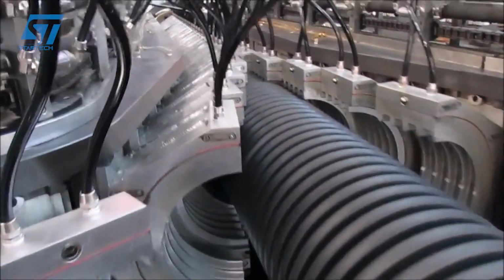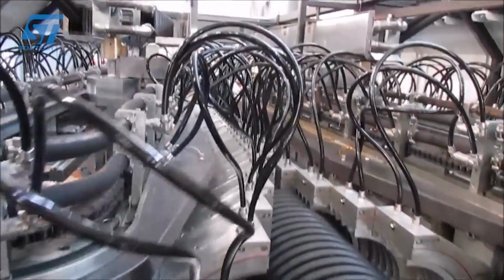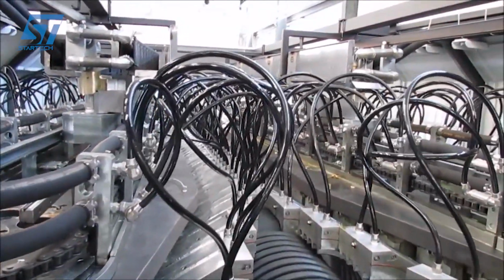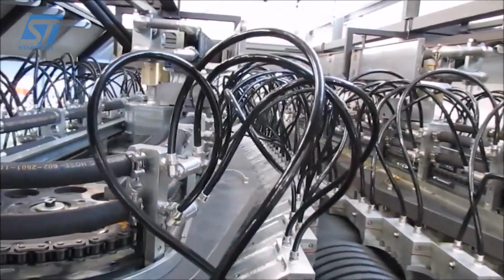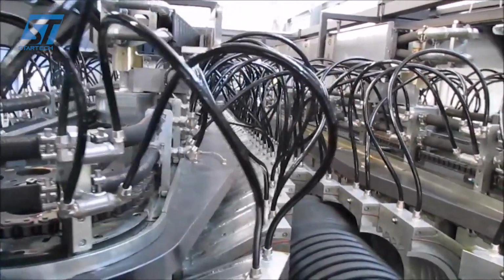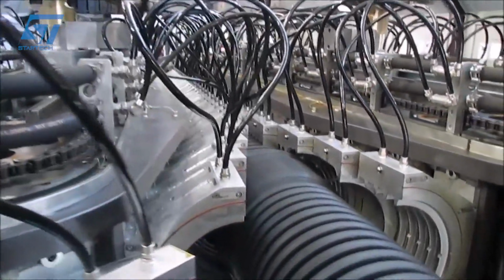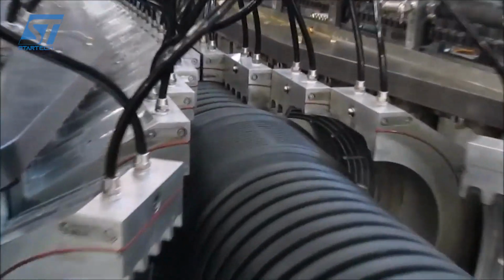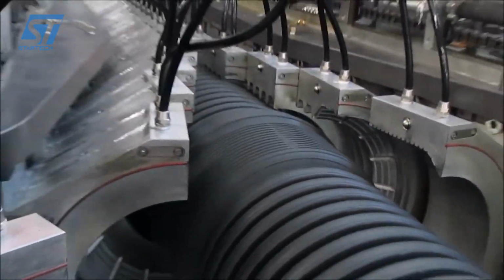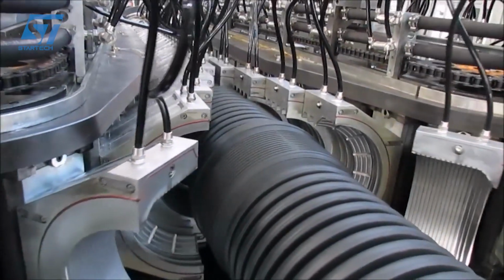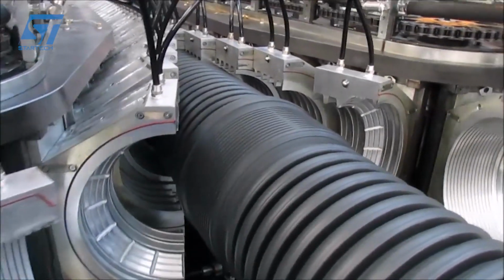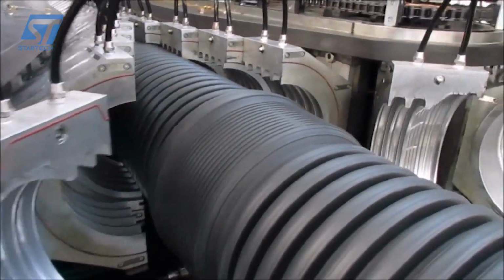Neptune Plastics uses a modern extrusion line with two extruders. The main extruder extrudes the outer layer of the tube, forming the corrugated rib. The sub-extruder extrudes the inner layer of the tube, creating a smooth surface. The extrusion die is specially designed to create a double-layer structure with corrugated outer ribs and a smooth inner surface.